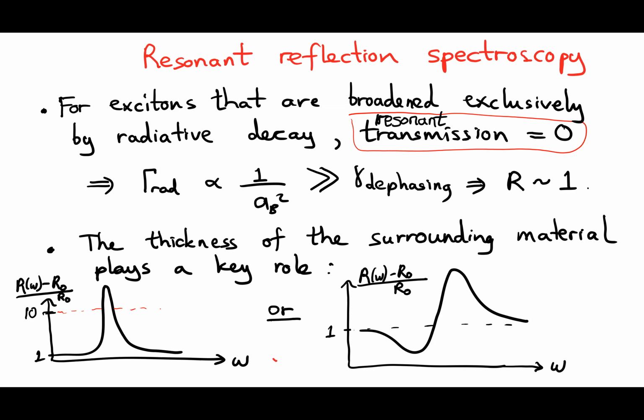But in practice, there's always some background reflectivity, and the phases of the reflected light at different interfaces are different from that of the light generated by the excitons. And that results in these Fano-type dispersive line shapes, which are generic to most experiments. Okay. So this is the elementary signature we're looking at. We want to find out how strong these optical resonances are and how they change in the presence of, say, electrons or other external perturbations.